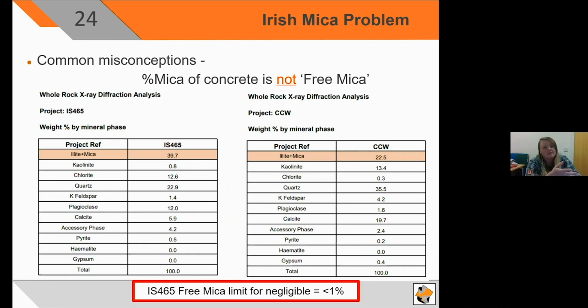We did a little XRD analysis on both of these. So on the left, you have the typical Donegal phyllite, which produces 39.7% total mica, and our good aggregate down here, which is the China clay waste, gives 22.5% total mica. Bear in mind that the IS 465 free mica limit is less than 1% to get a negligible classification.